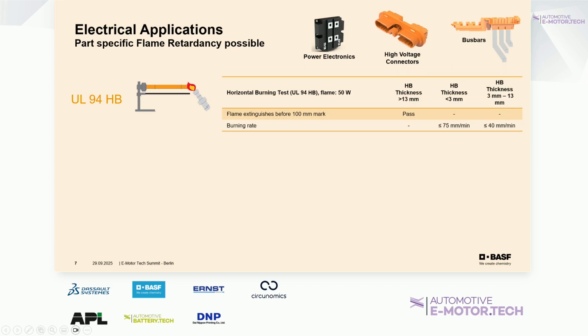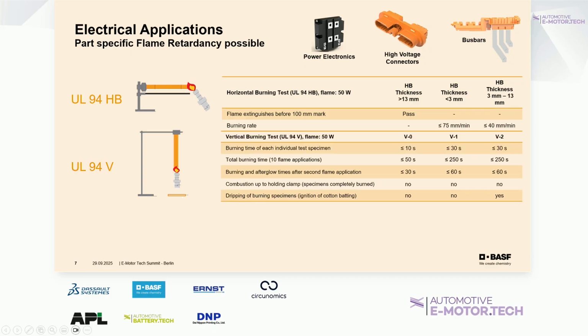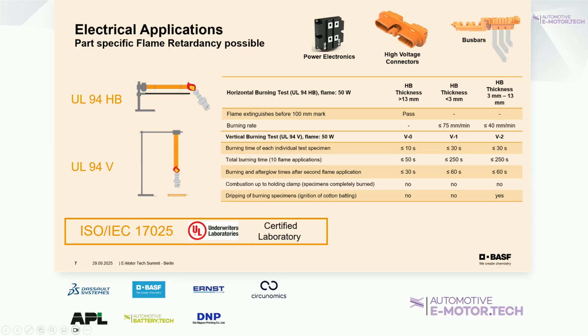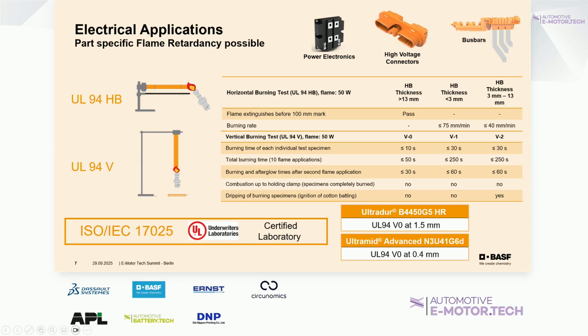If we look at electrical applications, what we typically see as a huge trend are materials which withstand the so-called UL94 test. It's a burning test, more or less. You have a test specimen, you burn that specimen, and you want to see the behavior. Does it still burn or not? At UL, you have different classes, so-called HB, horizontal burning, V0, V1, and V2 classification. At the end of the day, they all give you different results based on your plastics.